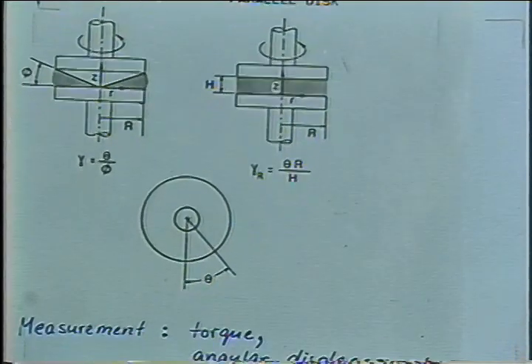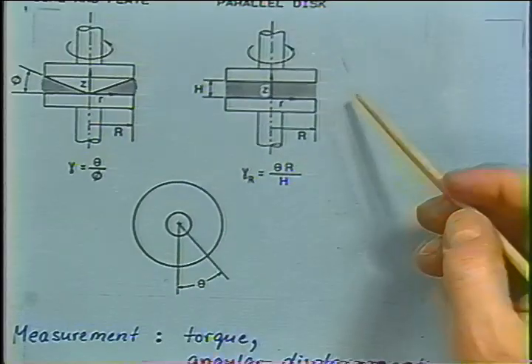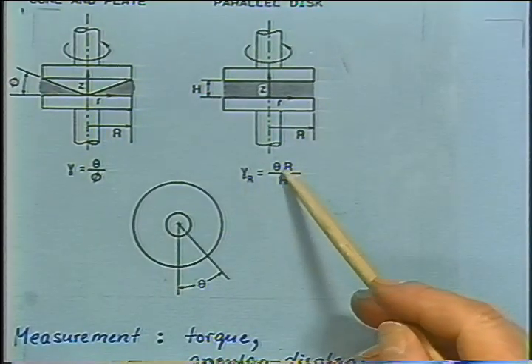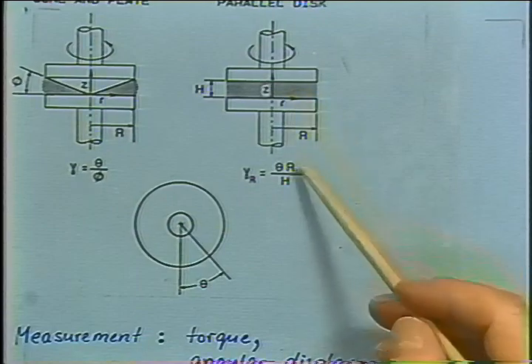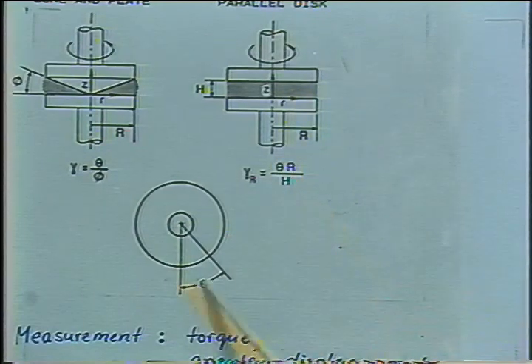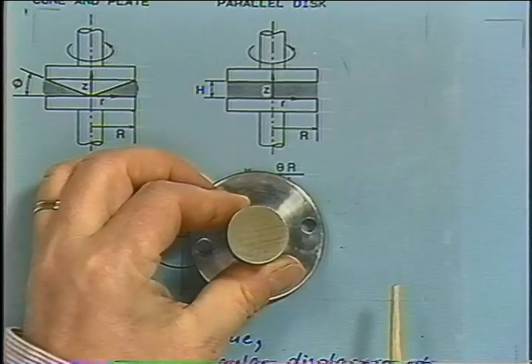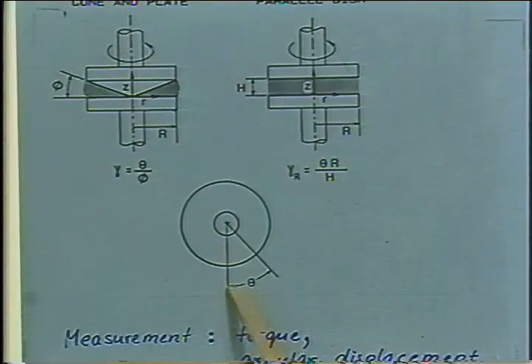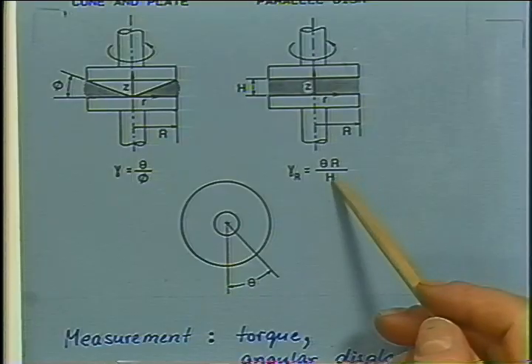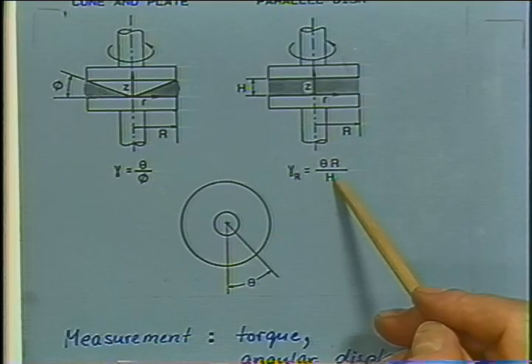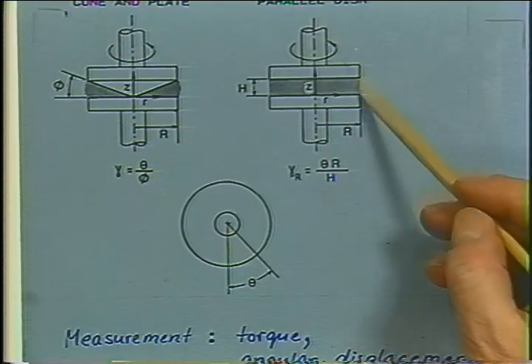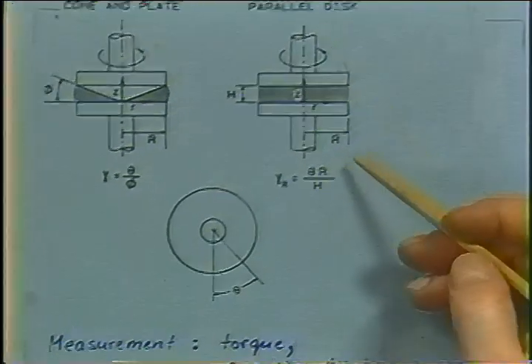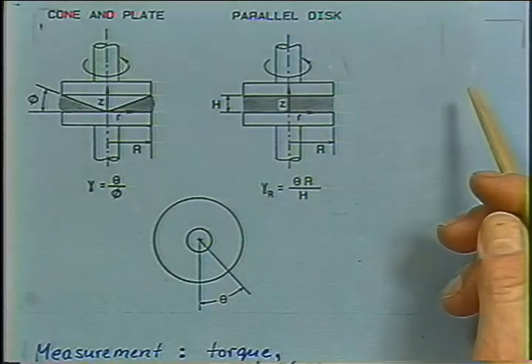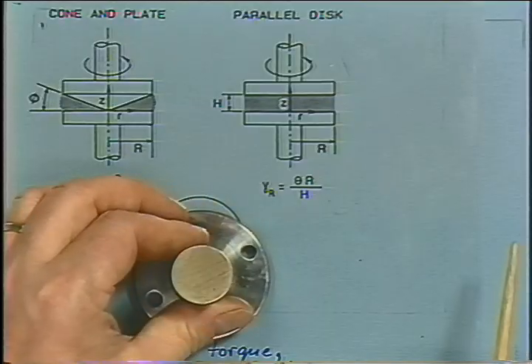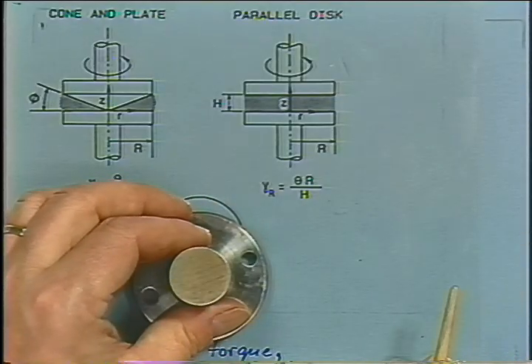You could produce a large shear strain in the sample by changing the sample height. You would introduce an angle theta. You would rotate your plate by some prescribed angle theta, and just do this. You would do this with a thick sample, and you would obtain a small strain, or you would go to a very thin sample, and you would get a very large shear deformation in your sample, but still your total angular displacement would be small, and the experiment would be okay.